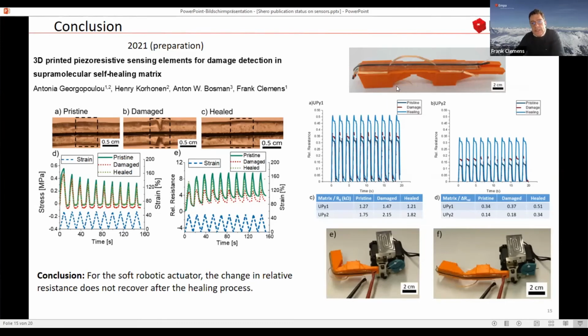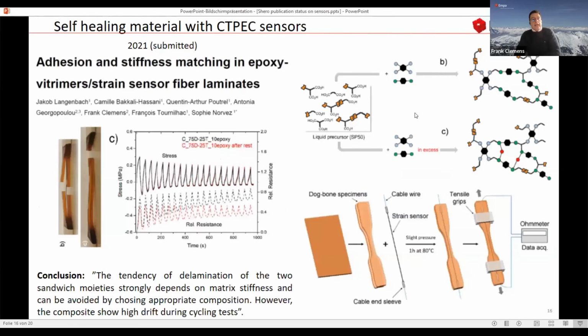Another approach which we did: these were tensile experiments, and now we did the bending experiment. When we do the bending experiments, unfortunately we do not get these perfect results from the tensile tests, and you can see that the relative resistance still changes continuously. We always have an increase in the relative resistance between before damage and healing.